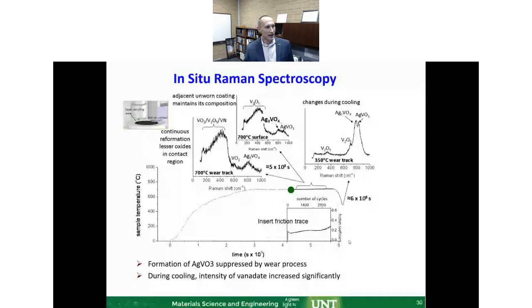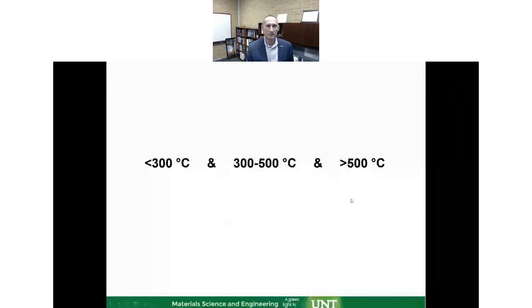When we cool it down and do the post-mortem analysis at room temperature, that peak here gets masked by some other oxide, like you see here, a vanadium pentoxide showing up. So it is not clearly identifiable. There's another oxide showing also here, as you can see in in-situ. So in-situ is a very clear presence. This is the power of this technique because it tells us exactly what is present at this temperature, and not what is left after cooling, because you form a different oxide.